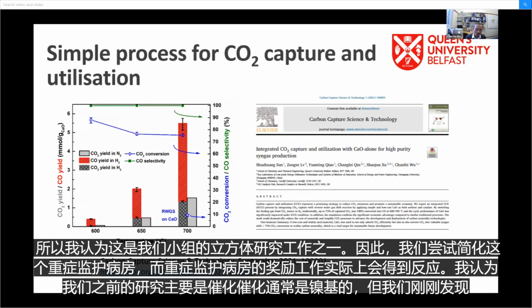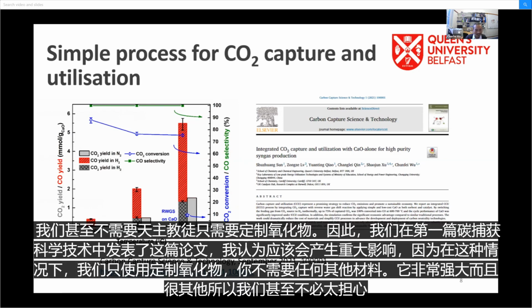This is one of our group's key research works. We try to simplify ICCU. For the ICCU reverse water gas reaction, our early work mainly involved a catalyst and a sorbent. The catalyst is normally nickel based, but we found that we don't even need a catalyst, just calcium oxide. We published the first paper in Carbon Capture Science and Technology. I think it should have a significant impact because in this case you only use calcium oxide, and you don't need any other materials.